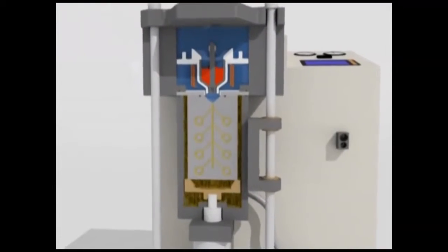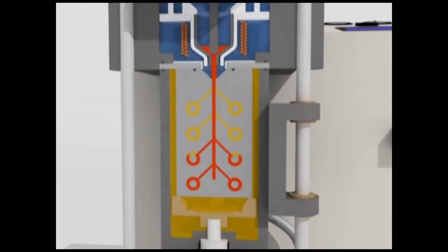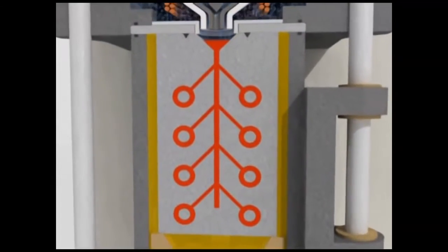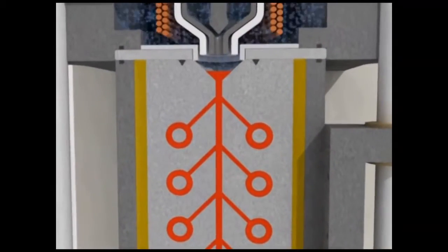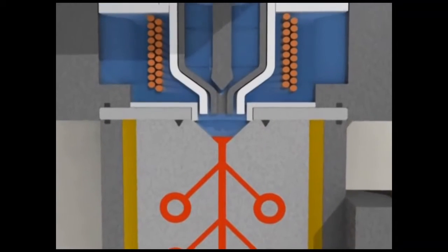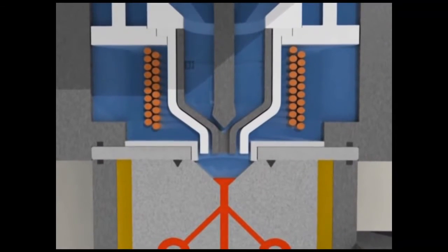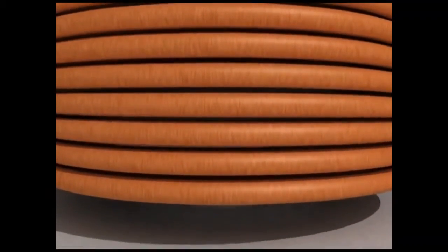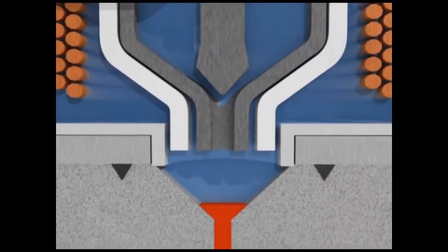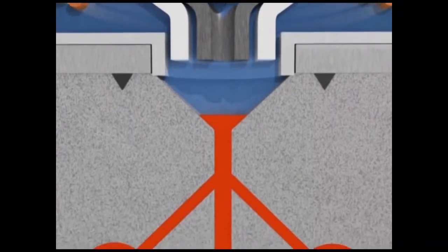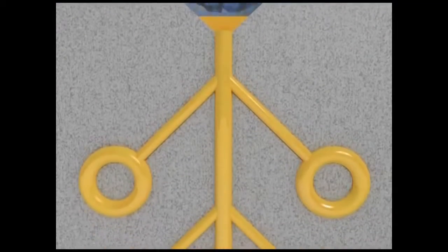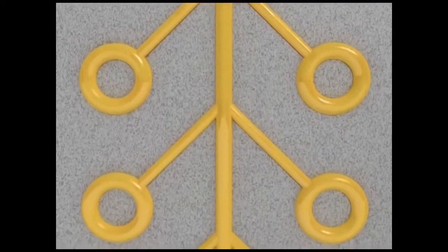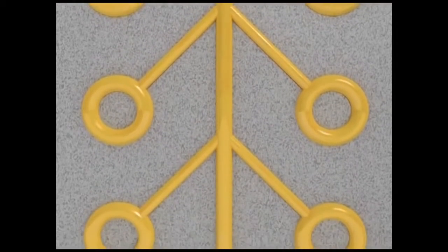The metal, once completely poured into the flask, is pressurized by argon up to 4 bars. This pressure, being applied to the molten metal, forces it into the mold while the vacuum pulls it. This results in a very smooth surface due to the effect of the vacuum and a dense, well-compacted casting due to the overpressure, which benefits both thick and thin sections.